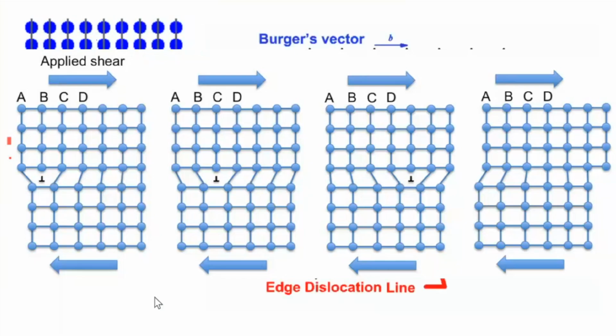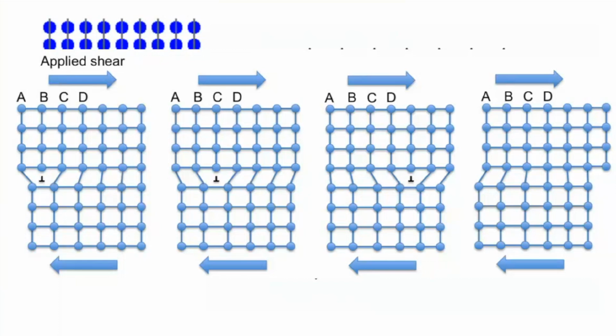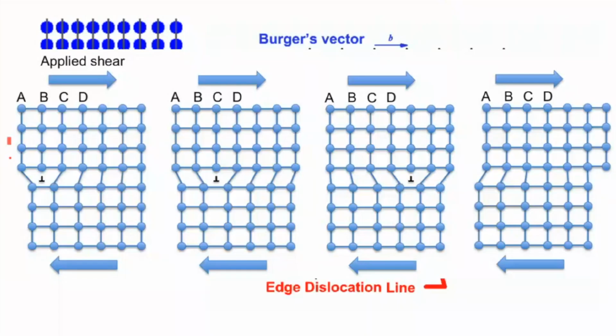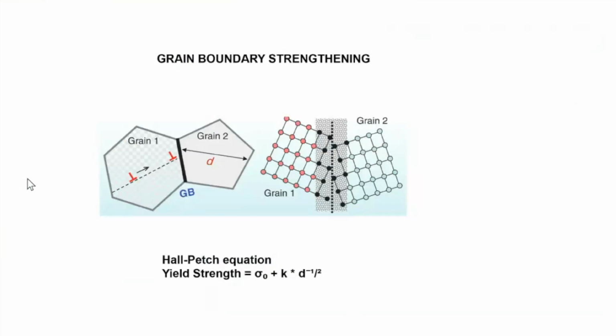It deforms much earlier. So the question is, how can I stop defect motion, primarily the dislocation motion? Of course, the easiest way is to stop it by grain boundaries, because two grains are in different orientations. If the dislocation cannot move through the grain boundary easily, then with a finer grain the material gets strengthened, and that is the normal strengthening procedure of aluminum alloys. You make it a finer grain size, and then the Hall-Petch equation comes in and you get a higher yield.